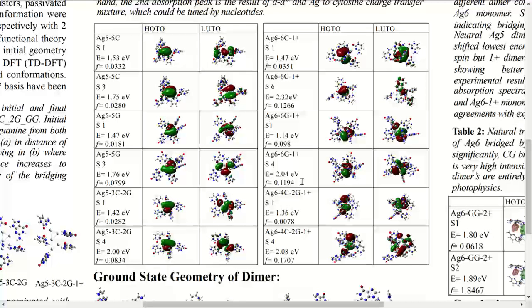And this is showing NTOs. So as I said, it's showing the transition nature. This one is mostly d to p transitions, silver transitions. But I had one question one time I faced, which is the contribution of s to d transition and d to p transition. I don't have a specific answer, but I'm going to include that in my new poster. I calculated this one. And for the main peak, the highest intensity peak, the main contribution is coming from the silver to ligand transition.